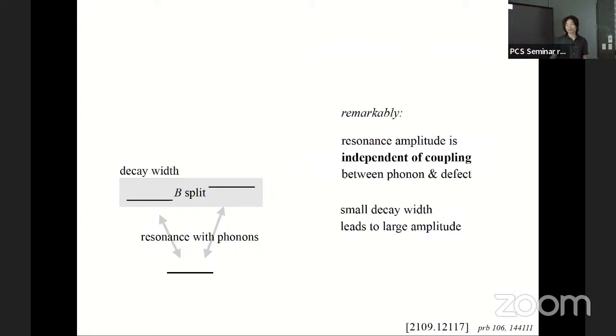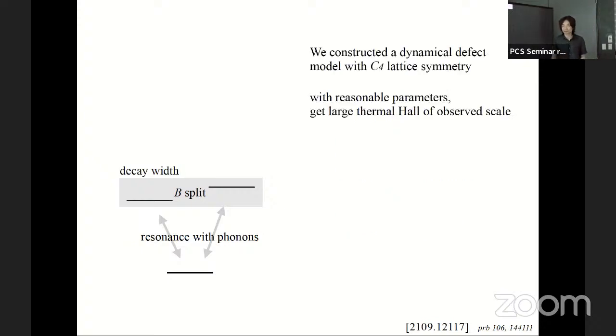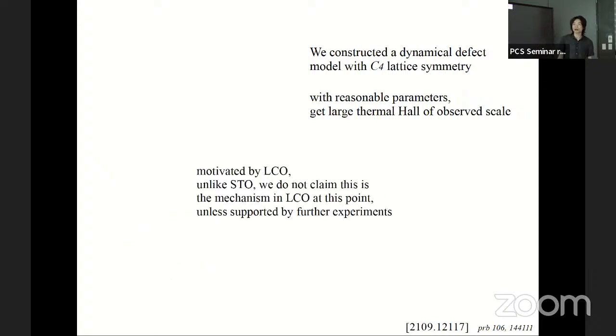Right, so these are some remarkable features of this mechanism. And so we constructed this C4 lattice symmetry picture. And if we assume some reasonable parameters, we can get a large thermal Hall effect of the observed scale. So it means we can reproduce this effect with reasonable parameters.